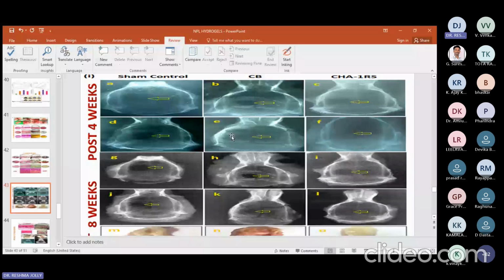But here, after 8 weeks, Cerabone was able to make the new bone. But the granules are not visible here in the radiovisiography. But you can see the granules in the histopath. So in X-ray, the Cerabone particles are not visible, but in histopathology, we confirmed that Cerabone was not ejected from the body completely. And this is our material after 4 weeks. The particles are there, but very little. And after 8 weeks, the particles completely got degraded from the body, and the new bone formation took place.